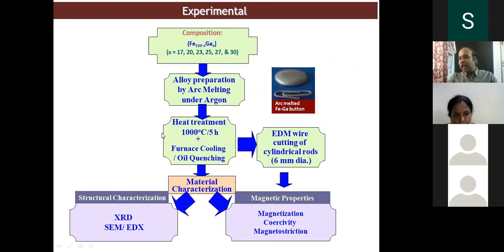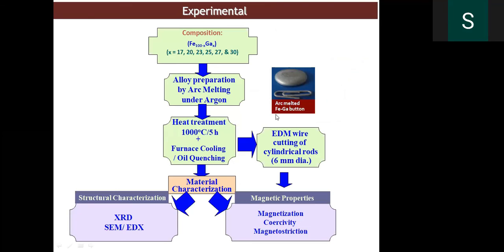in this development program. We process this material by a technique called arc melting, and we have taken the composition from 17 to 30. We have prepared the material by arc melting. We have heat treated at 1000 degrees centigrade, and we have adopted different cooling, furnace cooling, oil quenching, all those things. And this is how the alloy button looks. We cut this by EDM wire cutting, that is electrical discharge machining, and we have characterized it by XRD, SEM, EDAX, magnetization, coercivity, all the other things.